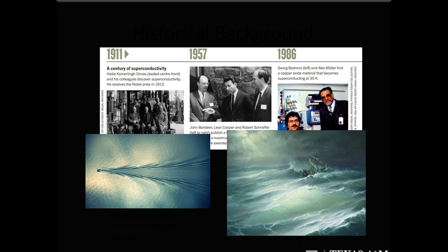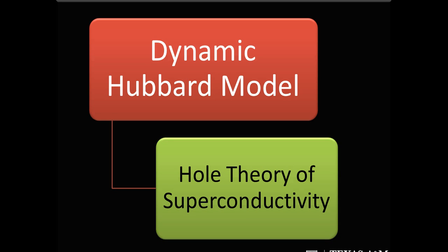BCS predicted a maximum critical temperature of 30 degrees Kelvin. So in 1986, when researchers found a superconductor at 35 degrees Kelvin, and later that year superconductors that went superconducting at 90 degrees Kelvin, it was a big surprise, and theorists set to work finding a model of how these superconductors behaved. One of the most prominent models was something called the dynamic Hubbard model, and the hole theory of superconductivity is an extension of that.